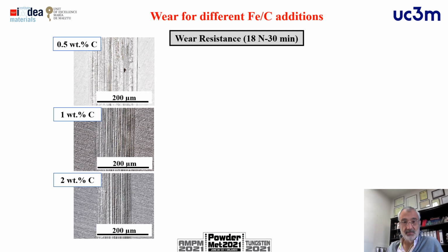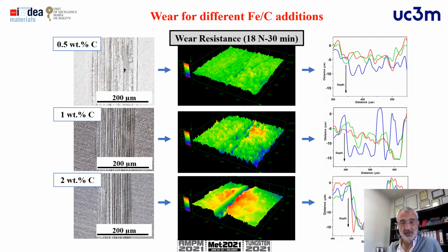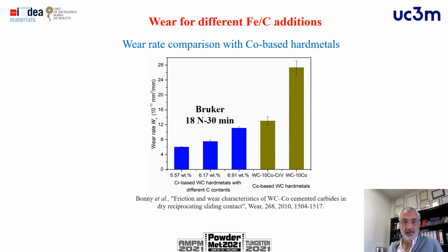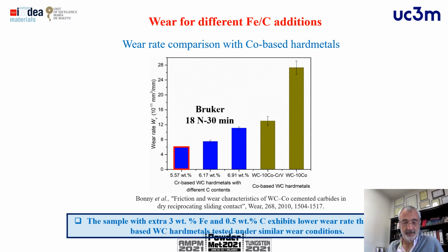Also, we have developed some wear resistant tests. We have done it in a Bruker tribometer in a dry sliding test with the system of ball on plate. We have used alumina balls, and here you can see the profiles of those tracks in the material. But if we measure the wear loss, the wear rate in comparison with conventional cobalt-based hard metals, which is here on the right in green colors. Here we have on the left our results, and the material that we have selected as the best one with 0.5% of carbon and 3% of iron got the best results in terms of wear rate, the minimum wear rate in comparison with all the other materials.